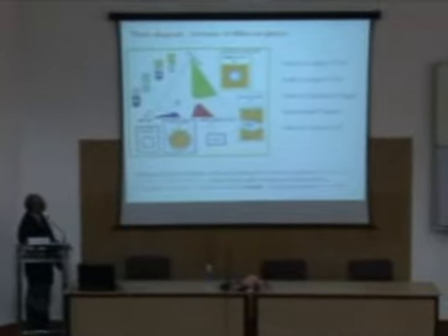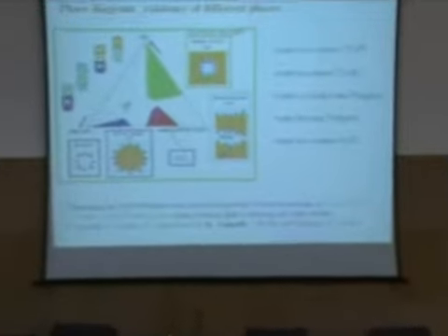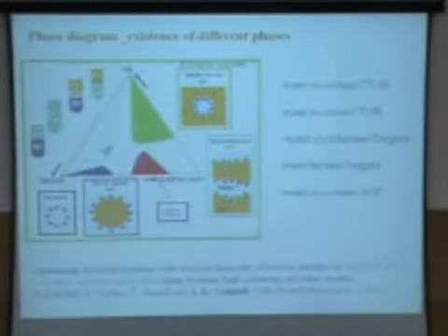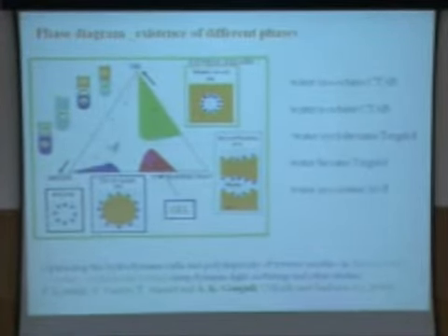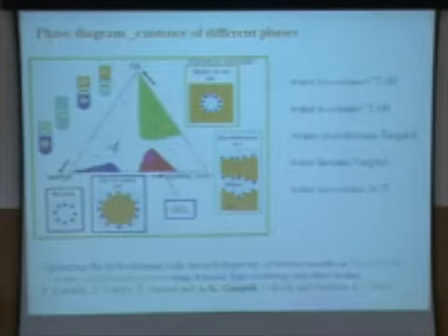Once you want to work with the micelles, it may be possible that you are not getting the right concentration. So, you are in a different part of the phase diagram, because you have three different reagents. You have a ternary phase diagram, and you have to understand which portion of that will give you the reverse micelle. Okay. So, what you do is you work with different systems and you generate a phase diagram and map out which part of the phase diagram actually gives rise to what kind of structure. Okay. So, once you know that, then you work with that composition.